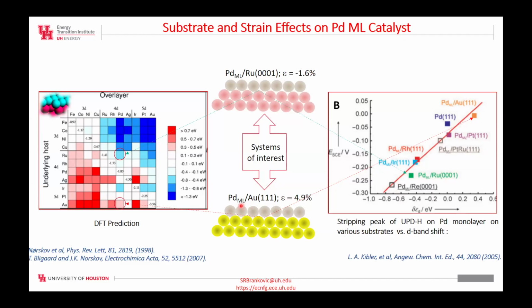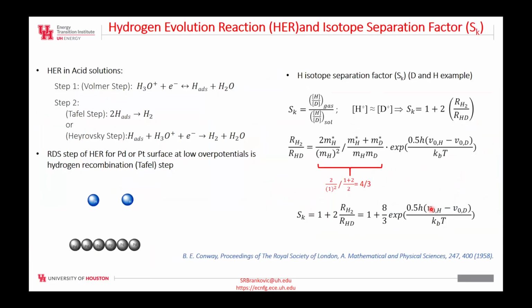So therefore, if you put a palladium monolayer on gold, you expect that the palladium monolayer should behave better, or act more actively, than the bulk palladium, which already is very active for electrolysis. If you put a palladium monolayer on ruthenium, you should actually suppress this activity. And this is first demonstrated by studying absorption of hydrogen, electrochemical absorption of hydrogen, on these palladium-covered different substrates. So therefore, we already have a prelude that points to the correct catalyst choice.